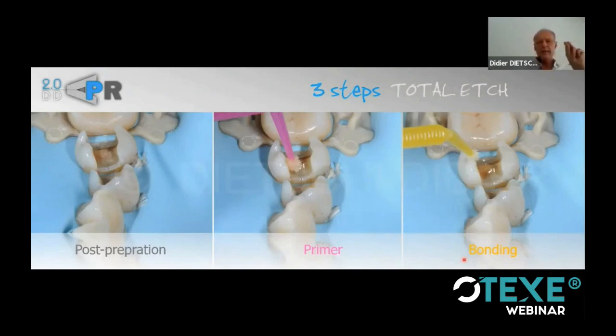You want to create a fully hydrophobic or mostly hydrophobic hybrid layer, which is impossible with any adhesive that will combine primer and bonding. Modern adhesives like universal adhesives are not bad products, but because they have in common this concept that they mix together primer and bonding, like the first generation of one bottle, one-step self-etch systems, they are likely to be less stable than classical adhesives.